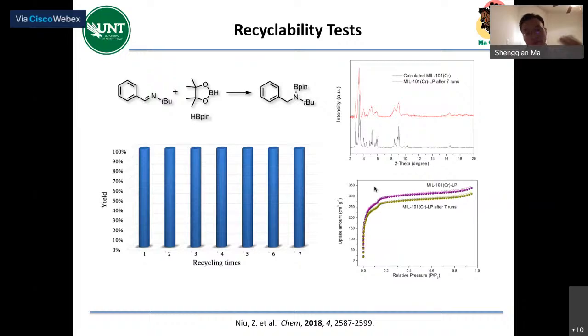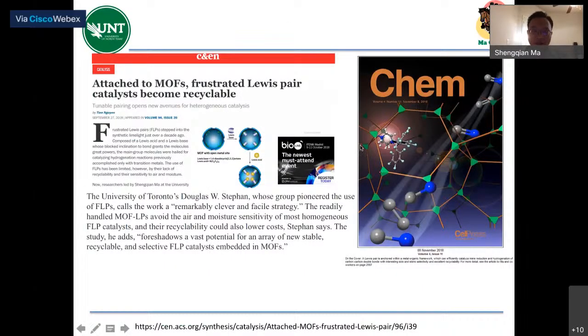Of course, one of the beauties of the MOF is that the heterogeneous catalyst we can easily recycle and regenerate, and also this MIL-101 is very stable. Barely, the structure can maintain, and there's barely any drop in the activity. It's mainly because of the loss during the filtration. So we're very excited, and also Professor Stephan is very excited and gave us very high comments. As he said, enormous, vast potential for this FLP and the MOF, and the opportunity, of course.